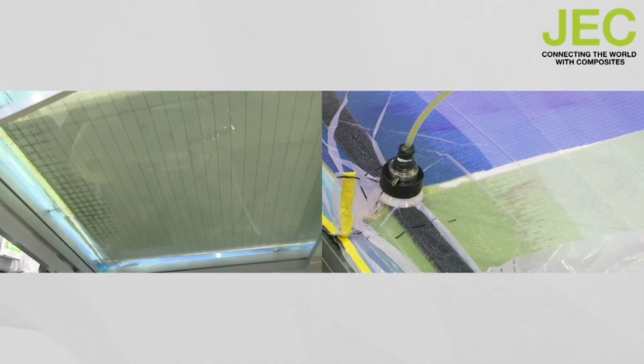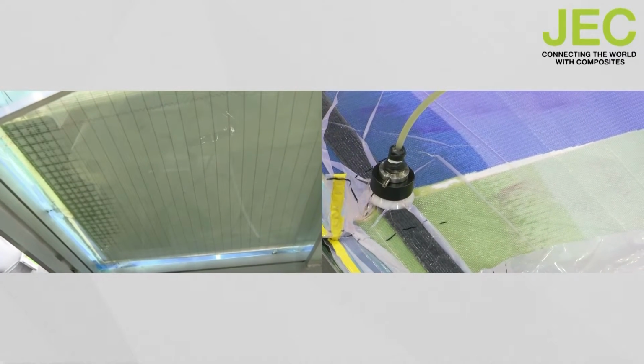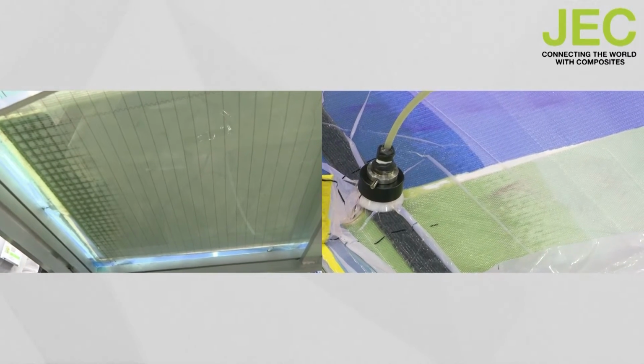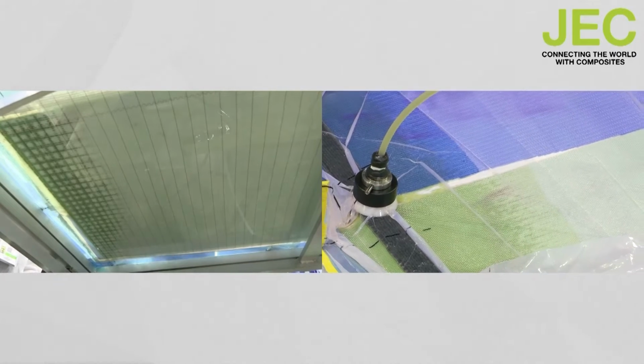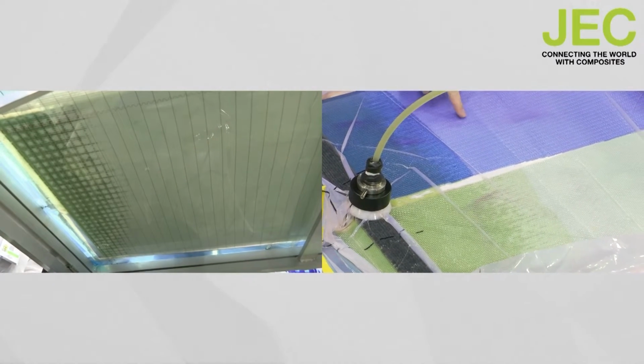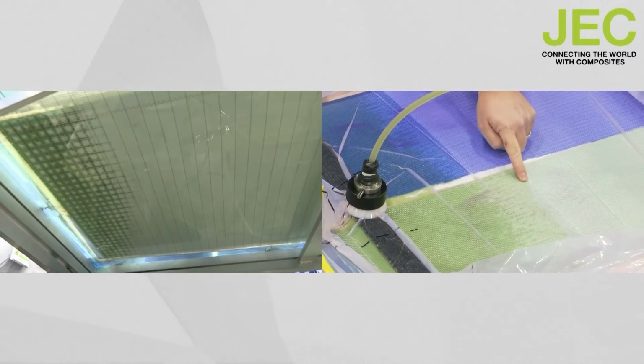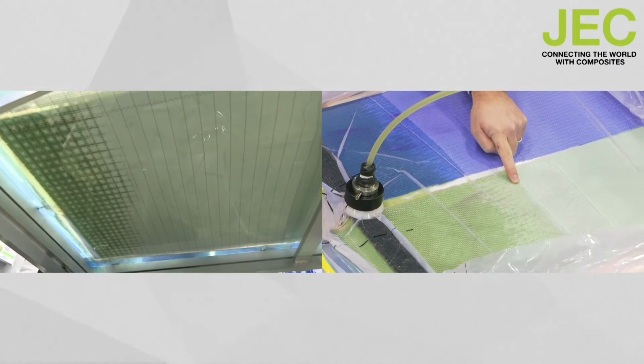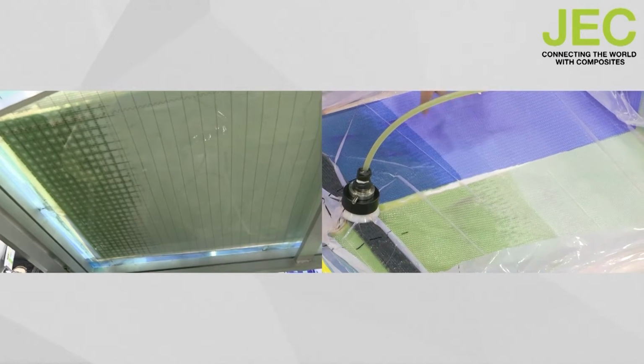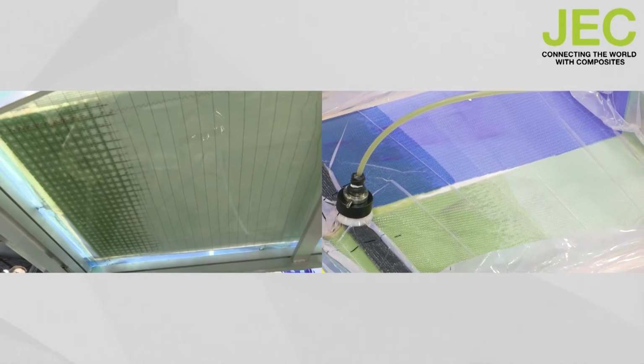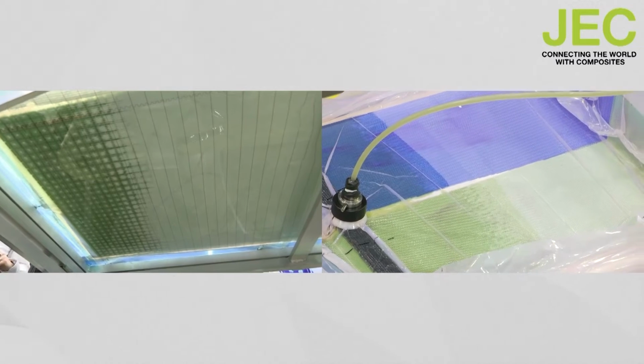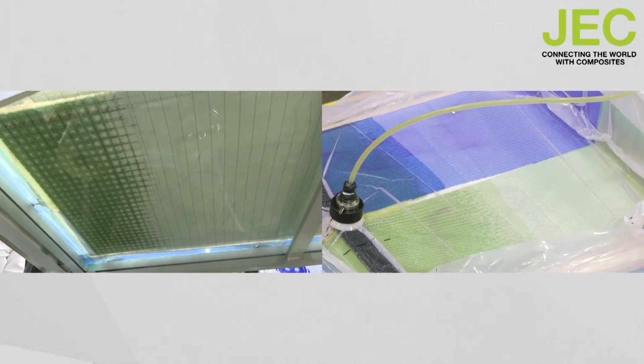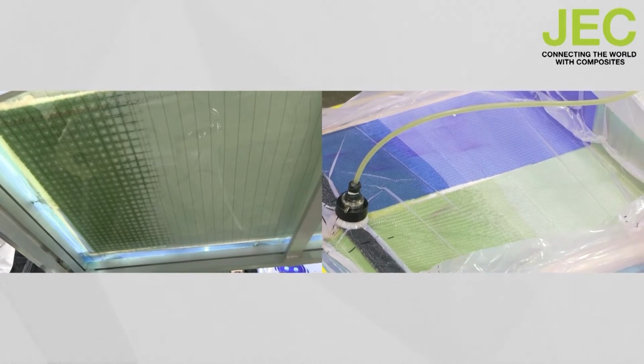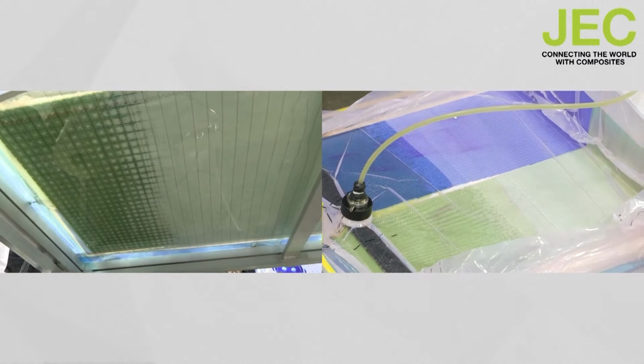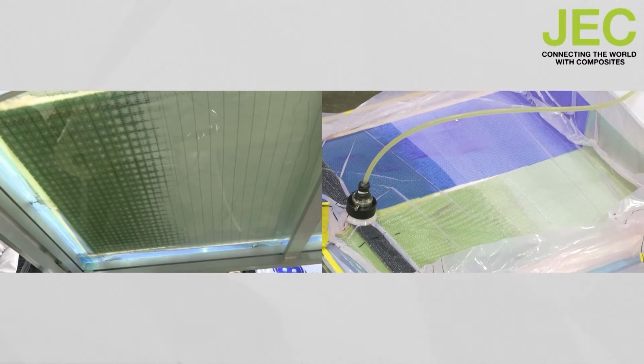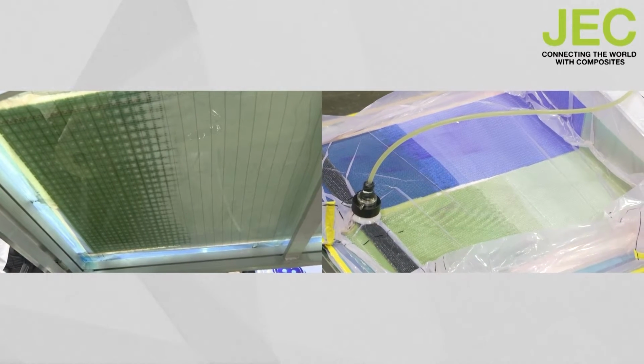Yeah, now you can see it coming through the bottom. So you can see testing on a glass plate is very useful because there's a lag. We're flowing much faster across the top in the high permeability area than we are on the bottom. And the core we're using is a closed cell foam, so it has to have perforation holes about every 20 millimeters. And it also has grooves against the mold side.